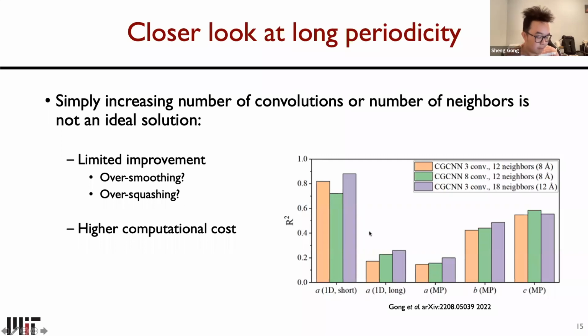And in this figure, we show the prediction of periodicity of one-dimensional chains and real crystal structures in the Materials Project database by the default CGCNN with 3 convolution layers and 12 nearest neighbors in each convolution, the CGCNN with 8 convolution layers, and the CGCNN with 18 neighbors within 12 angstrom. And we can observe some improvement for most cases by increasing the number of convolution layers and the neighbors, but this improvement is actually very limited.